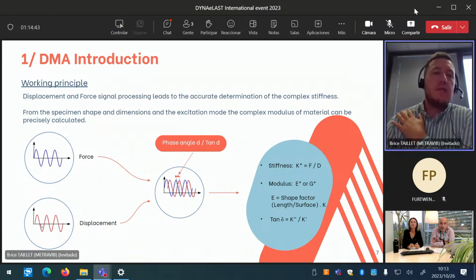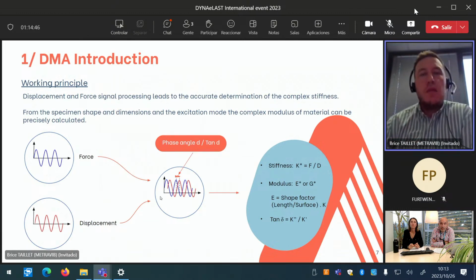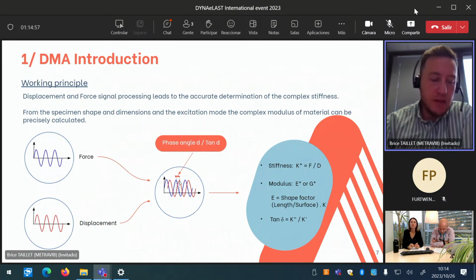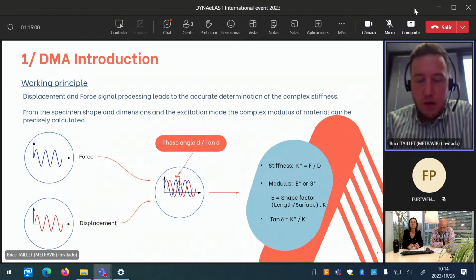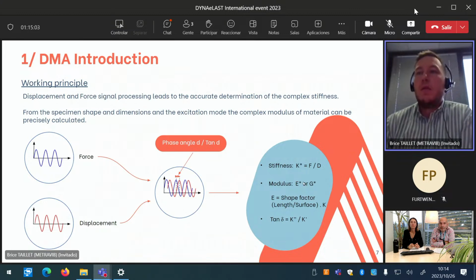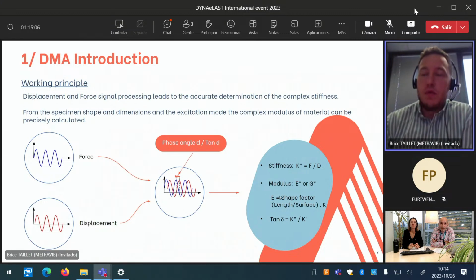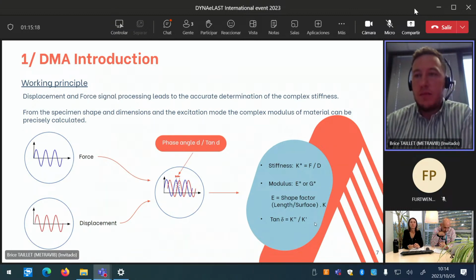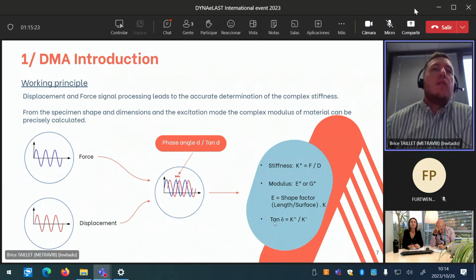With the displacement and the force signals, we are able to compute the stiffness of the materials. It's just a force under displacement. And regarding the shape factor of the specimen, that is to say, if we are working in tension, in bending, or in compression, in shear mode, with the shape factor, we are able to compute the modulus. And the tangent delta is just a simple combination between loss factor and E modulus. And tangent delta is just representative of damping properties of your materials.